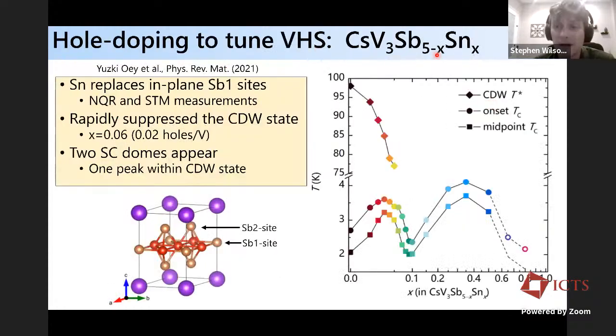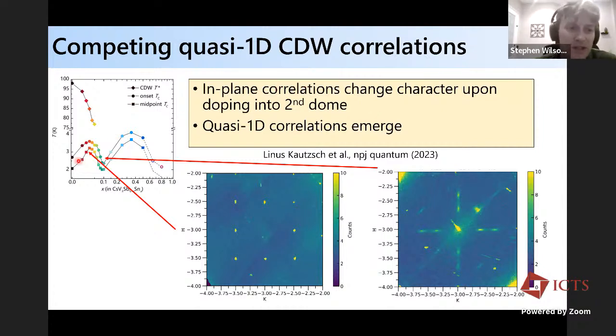Okay, so looking at the hole doping phase diagram, what you find, first of all, is that the charge density wave phase is rapidly suppressed, and you end up with two domes in the superconducting TC, okay? The first dome is within the charge density wave phase, and the second dome is outside of it. If we look at charge correlations of these two domes, in the first dome, slightly away from the first peak, in reciprocal space you have these charge superlattice peaks at these half-type positions, which is consistent with the 2 by 2 superstructure in the plane. But when you start to look near this phase boundary where you have a minimum in TC, you see that the charge correlations are dramatically renormalized, and they split away from the half position into these incommensurate positions, and they become diffuse in the direction that they've split in reciprocal space.